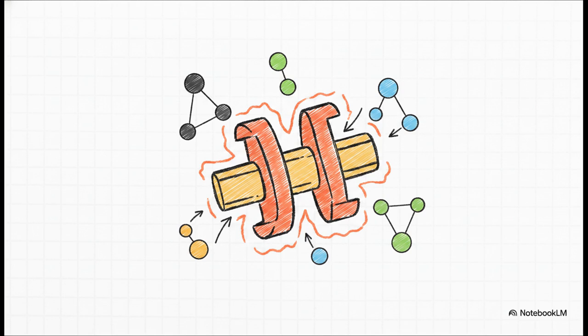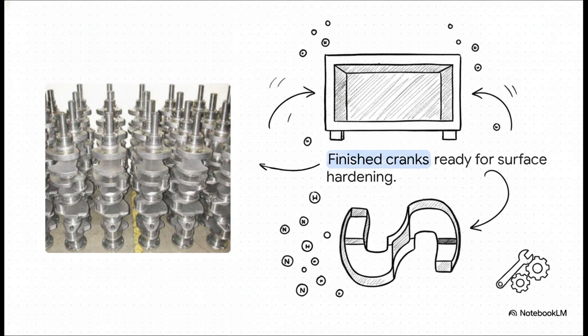Because of that specific chemical recipe, it retains immense toughness even after being heated to over 1,500 degrees Fahrenheit. We're talking about a massive yield strength of 162,000 psi. But we're not quite done yet.